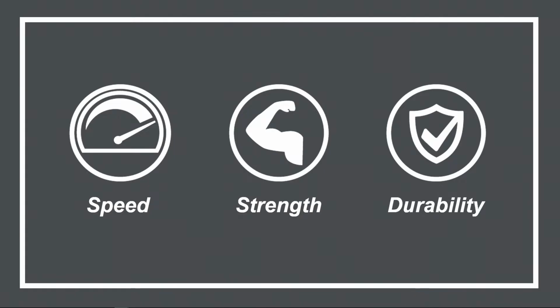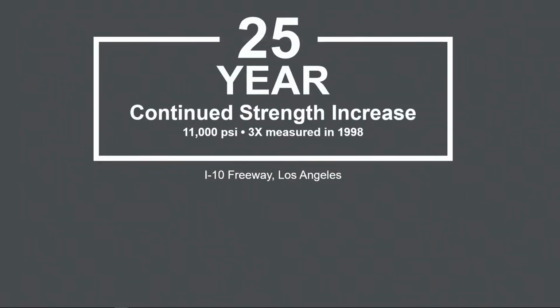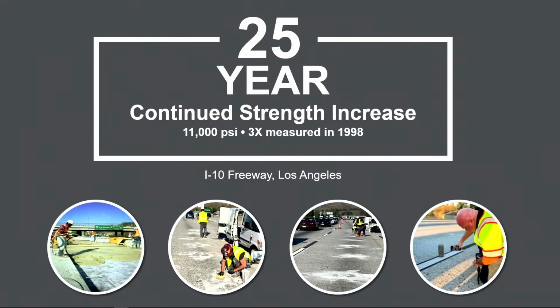long life durability. Speaking of durability, back in 1998, Caltrans installed 2 lane miles on the I-10 freeway in Los Angeles using RapidSet cement concrete. Fast forward 25 years, and we were able to go out and test that in-place concrete. What we found is that concrete, after 25 years in the Los Angeles freeway, had a measured compressive strength of over 11,000 PSI and a calculated flexural strength of almost 3 times what it was at opening back in 1998. So that concrete will be in service for the next 25 years.